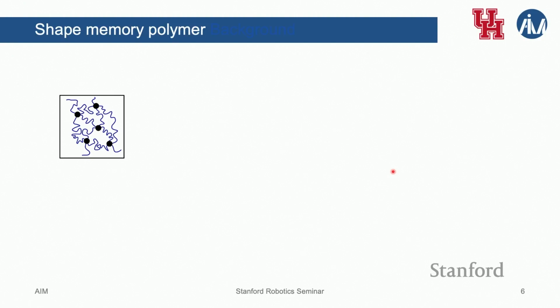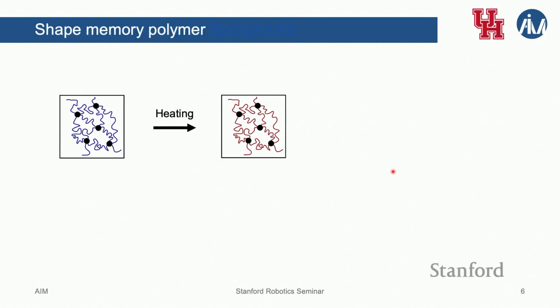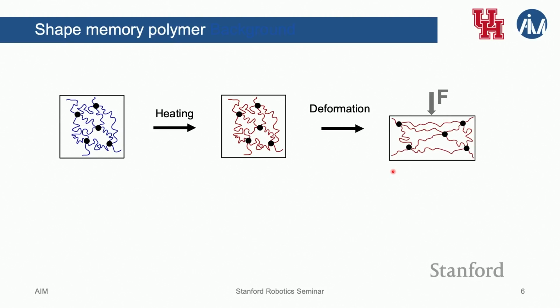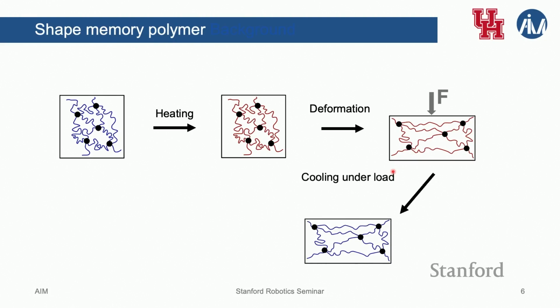This is just an idealized version of a polymer chain at room temperature. And we first heat it to above its glass transition temperature, in which the phase transforms from the glassy phase to the rubbery phase. And now it's much more compliant. In this state, we apply a mechanical deformation. We change its undeformed shape to something that's deformed, and desirably deformed. So we go from shape A to B. This is a manual step. We have to apply some force for it to do this. And while we keep it in that shape, we cool it down. So we just hold it and we plunge it into an ice bath, let's say.